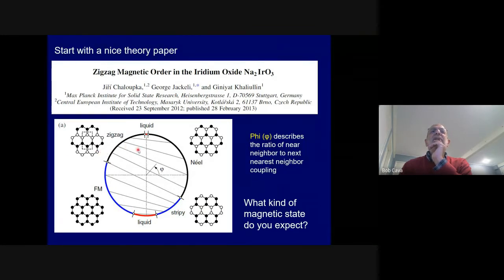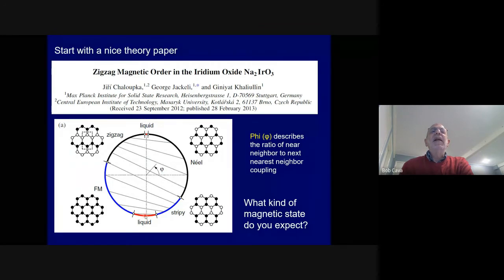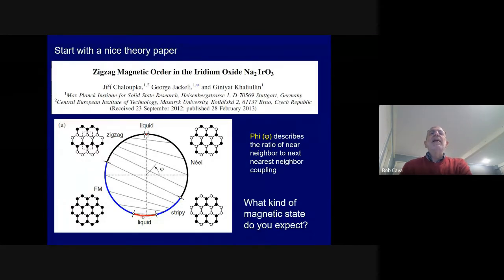And the theorists realized at some point that if you change the ratio of near neighbor to second nearest neighbor interactions, you can switch between these states, the Néel state, what's called stripy state, ferromagnetic state, and zigzag state, by changing the ratio of the magnetic interactions. And this chart right here motivated a lot of our work subsequently, because on this chart, there are two regions where we expect to find a quantum spin liquid. So we began looking for quantum spin liquids in these two regions, and you can try to adjust that yourself, or you can hope that nature gives you a material that does that.